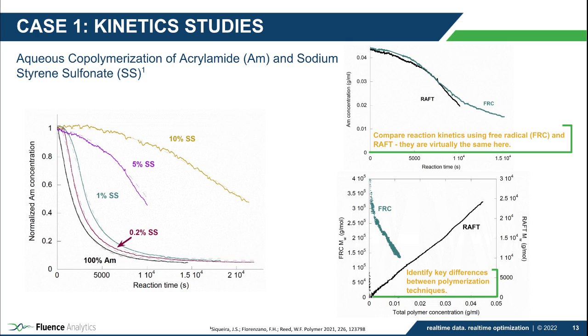On the right side, we show the comparison of the same reaction carried out with FRC and RAFT, and we have found that the kinetics are virtually the same, but that the characteristic molecular weight trend is very distinct. A monotonic decrease can be seen for FRC, where the chains initiate, propagate, and die very quickly, and a monotonic increase for RAFT, living chains propagating simultaneously throughout the entire reaction. Given this stark difference, real-time monitoring can also help operators in industry visually inspect bad batches where control has been lost, saving money and time.